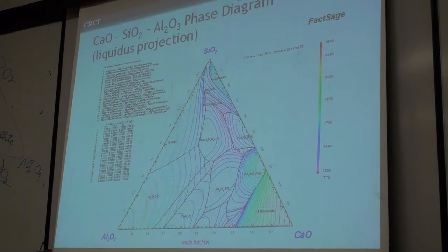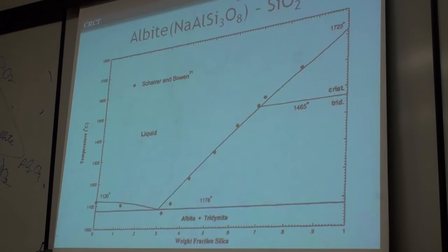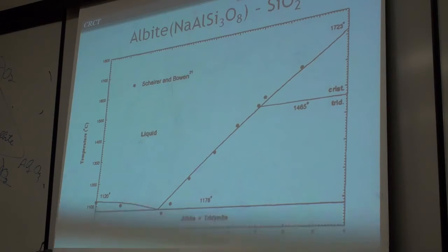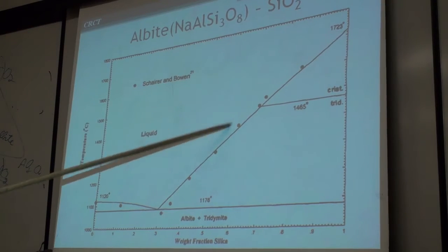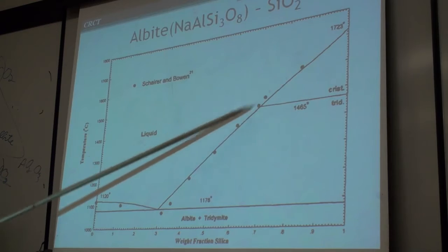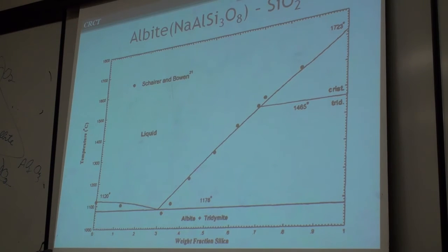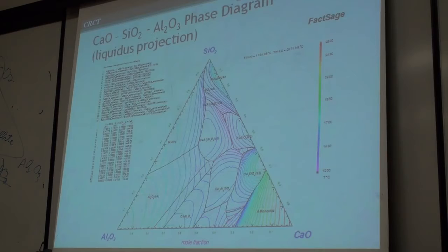I think the best evidence, there's also NMR evidence, and you can do molecular dynamics, and you always end up with these Al-sodium pairs replacing it. But the simplest evidence is this is an ideal liquid. You see, just NaAl is replacing silicon. So, charge compensation effect is very important.